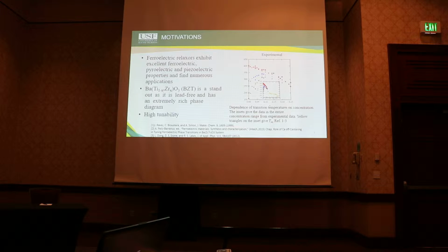Here we have the experimental dependence of the transition temperature on the concentration of zirconium, with temperature in Kelvin. The inset shows the entire temperature range. It's important to show the inset because after about 40% zirconium, the polarization of the cell is essentially zero, so we transition to using the maximum of the dielectric constant to determine where the phase transition is occurring. We can see in the experimental data that around 10% a pinched phase transition occurs.